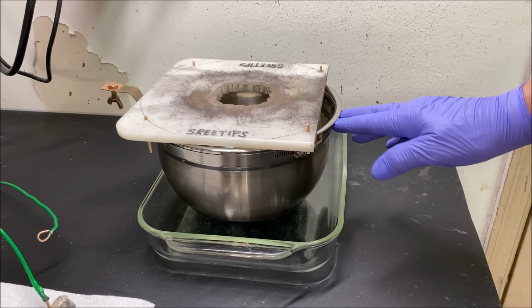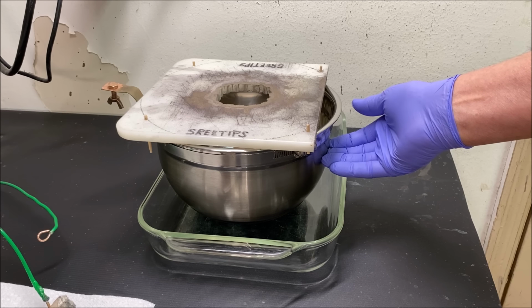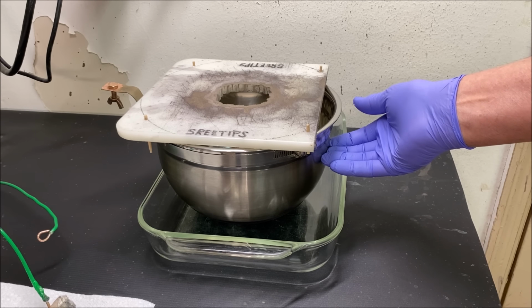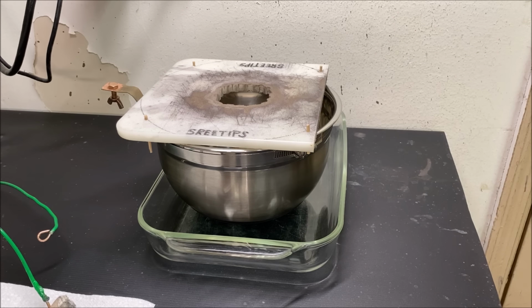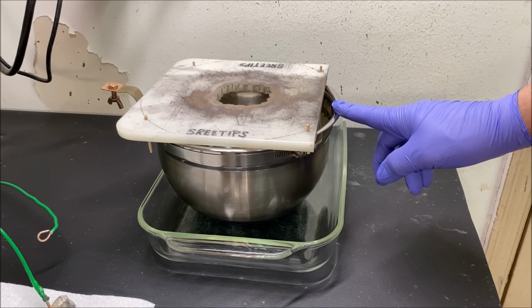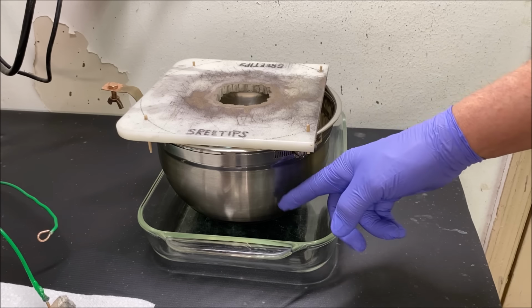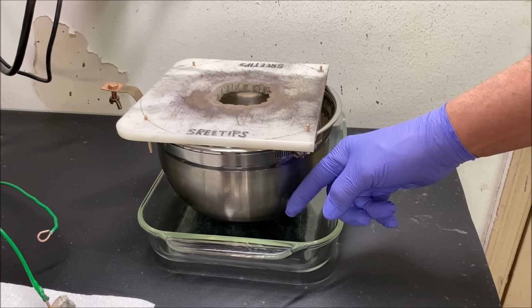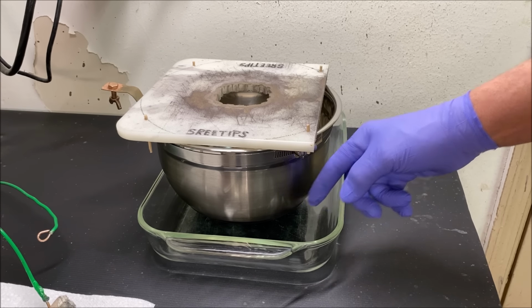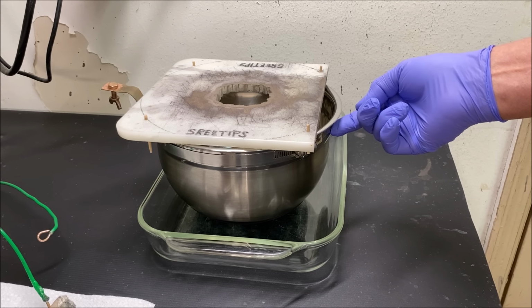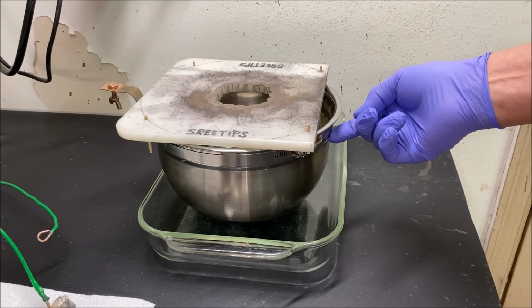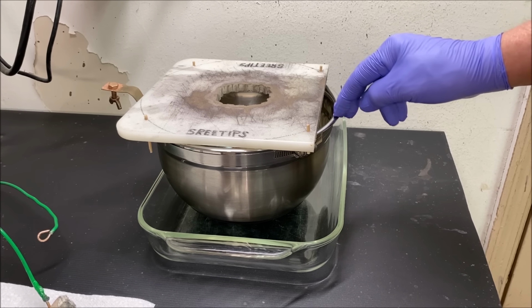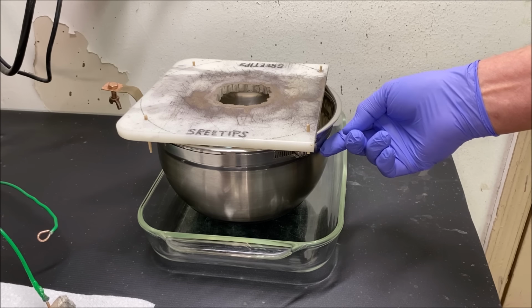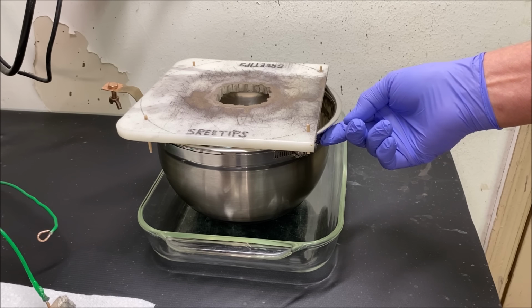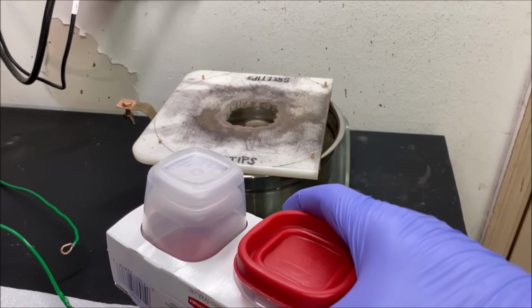because the electrolyte level drops as the cell operates due to evaporation, plus the concentration of the silver in the electrolyte depletes as the cell runs. It plates out as pure silver crystal on the inside of the cathode stainless steel bowl. So the concentration and the actual physical level needs to be adjusted as the cell operates to ensure we got the proper concentration of silver in our electrolyte and the proper physical level of the electrolyte is maintained in the cell. These are the little cups that I use